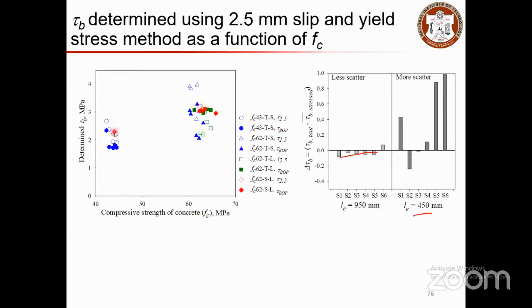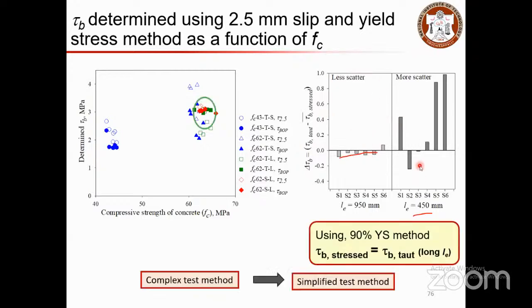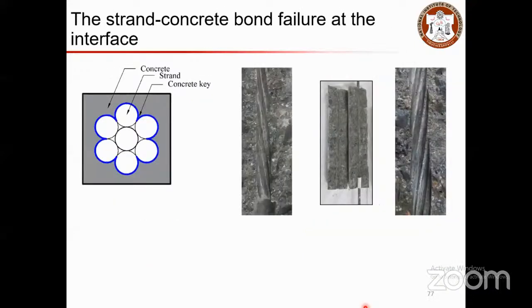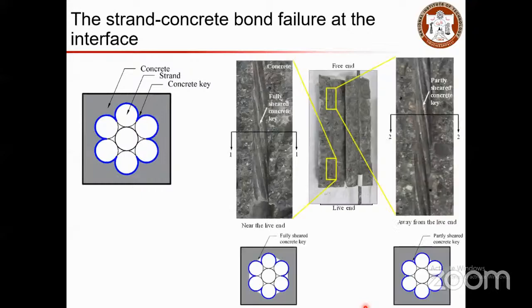With the 2.5 mm slip method, the effect of the length or compressive strength cannot be ignored. Whereas if you consider the yield stress method, there is a bend-over point where the behavior changes, and then the effect of the length and pre-stress levels is minimized. In that case, the scatter is also lesser. So from the complex test method, we could propose a simplified test method using this 90% yield stress method, and from this we could understand some bond failure criteria at the interface as well.